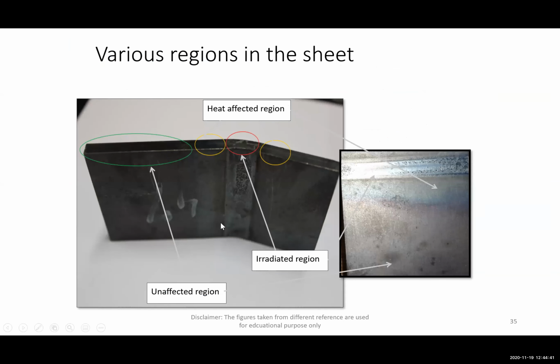So in fact, this is one sample which we have done with a 1 centimeter thickness sample. So in this 1 centimeter thickness sample, we are just passing it through a laser. So when we pass through a laser, you have an unaffected zone, you have an irradiated region, and this is your heat affected zone. So when you scan through a laser, obviously there is going to be a bending, and the major aspect, or I would say a major defect over here, is that earlier we thought of employing this directly for the actual condition of brake pedal and clutch pedal. But the major issue we observed is that because of the heat affected zone, when we went for cyclic loading, a huge amount of failure was observed. So that is the reason we didn't want to go in that particular direction.